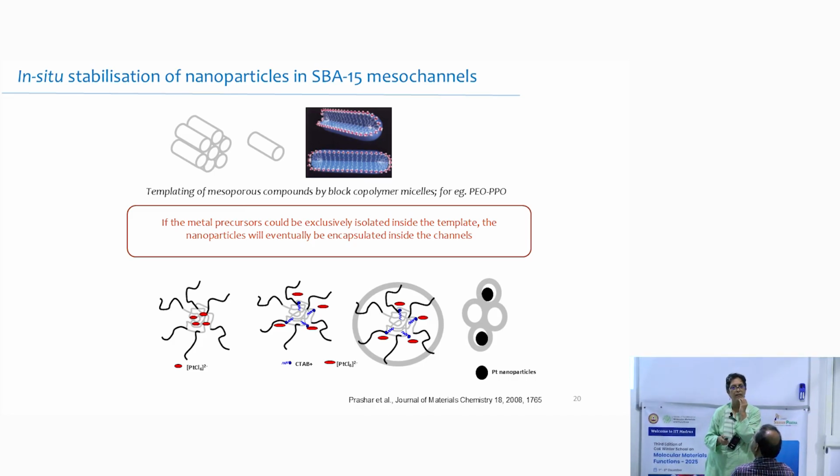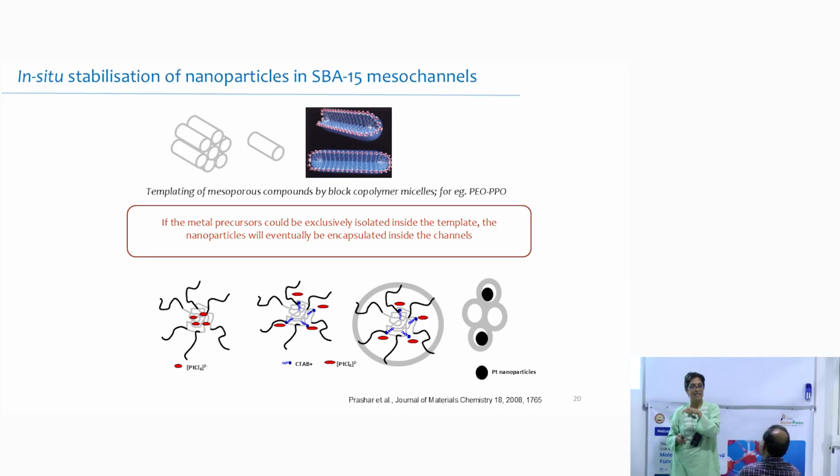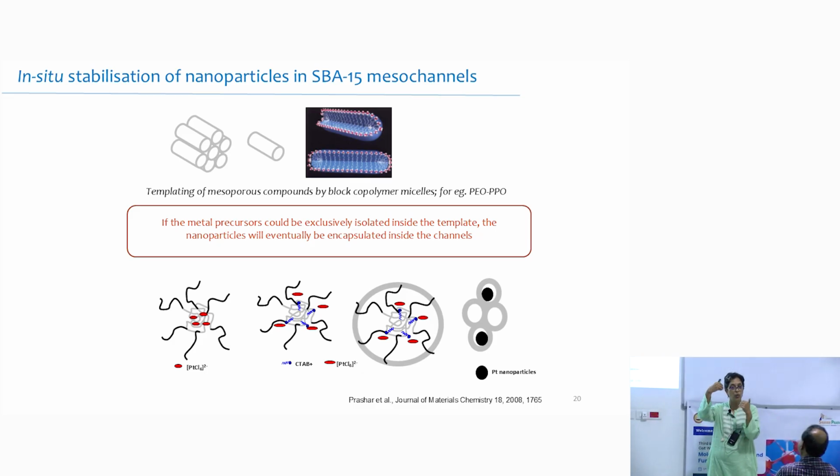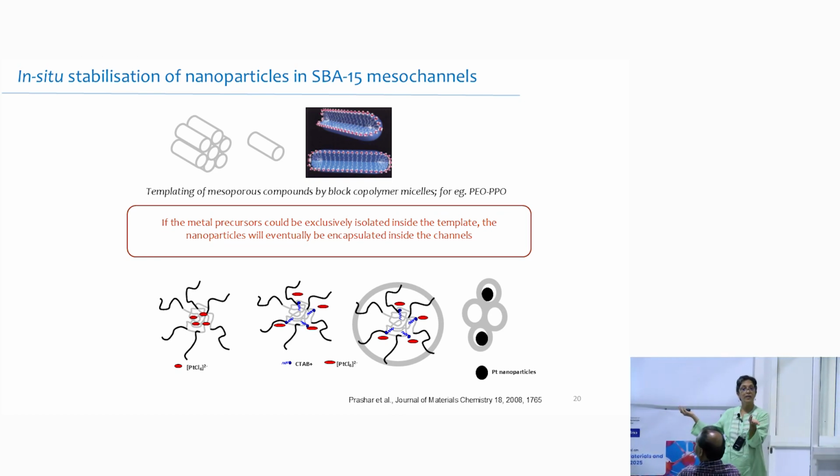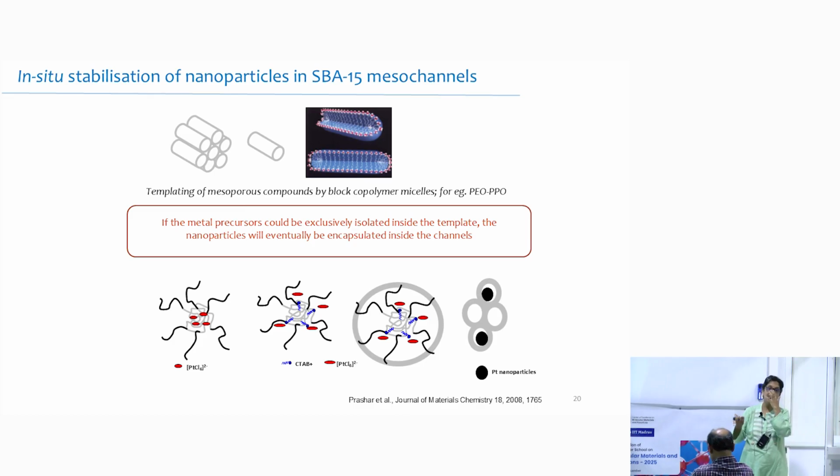Agglomerations can be prevented by addition of some emulsifying or suspending agent. But that is for protecting agents. They will go and sit on the surface of the catalyst, right? They are forming agglomeration due to some interactions. Yes, so what I'm thinking, with addition of some emulsifying or suspending agent, they will not interact with each other. They will repel each other. Yeah, they will repel each other, but they'll be covered with the protecting agents. Then when I'm doing the catalysis, they may not have that kind of access to the surface. That is why nanoparticles are stable, right? People are making nanoparticles which are stable. But the problem is that then catalysis may not happen. Activity may be less.